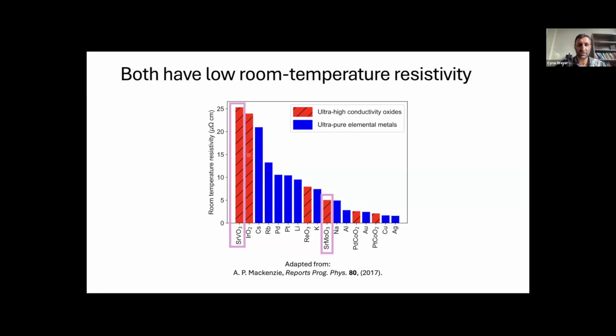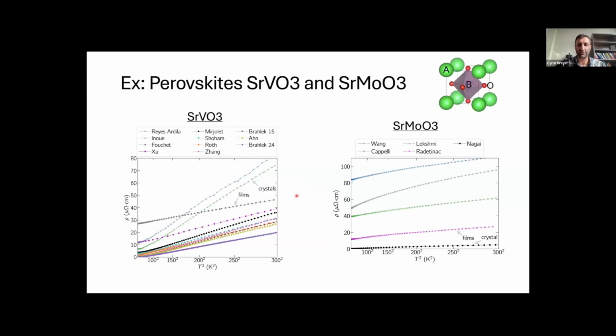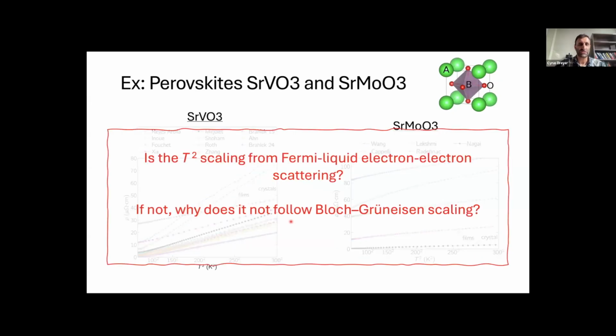So these are materials which are not strongly correlated, but they show this T squared up to high temperatures where we'd really expect them to act like normal metals that mostly show electron-phonon driven resistivity. So what is going on? Why do we get this T squared scaling? Why don't we see what we would normally expect from electron-phonon?